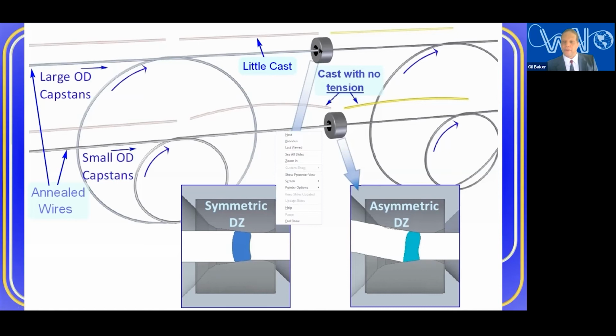Now, let's say they both go into this die. This one goes in straight, and there's very little asymmetric residual stresses. There are still residual stresses, but because the wire is symmetric, the deformation zone ends up being symmetric. And this, in turn, the wire comes out symmetric, like this yellow wire here as an example, with no tension.